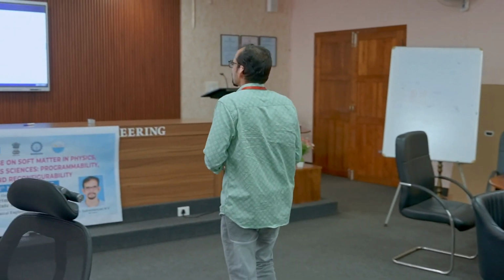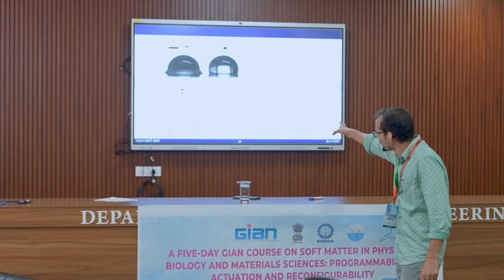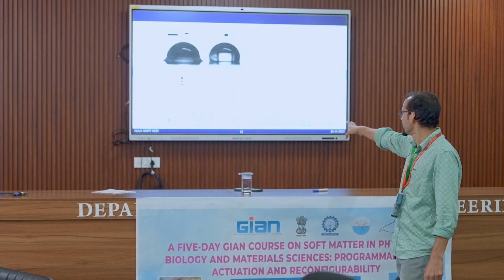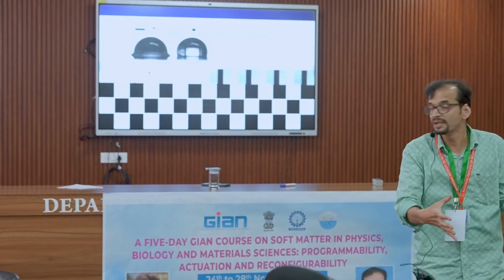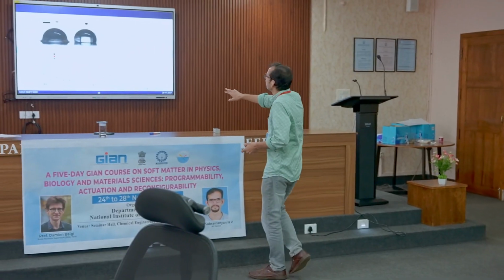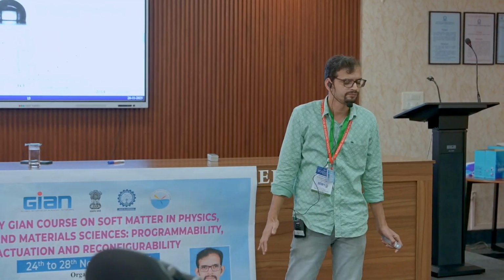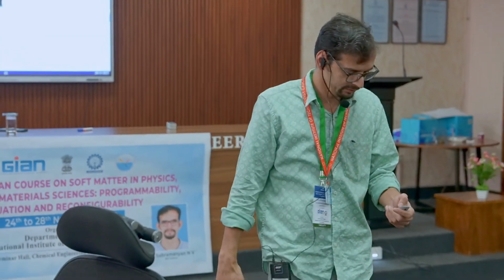Then you can see the velocity as a function of tilt angle. You see the droplet, depending on the different viscosity, at a 2-3 degree tilt angle, it starts to move, right? That means now you have a surface having a contact angle of 90 degree and a hysteresis of 3 degree. This is amazing, right? Because contact angle of 90 degree means, this is one of the most desired structure where you have a large surface area you can do. And this 3-4 degree hysteresis means you have sufficient control over it and you can control the velocity as well. It's amazing, right? And the velocity as a function of droplet volume should increase because gravity is the driving force, right? There is no surprising thing, but in paper we put it.